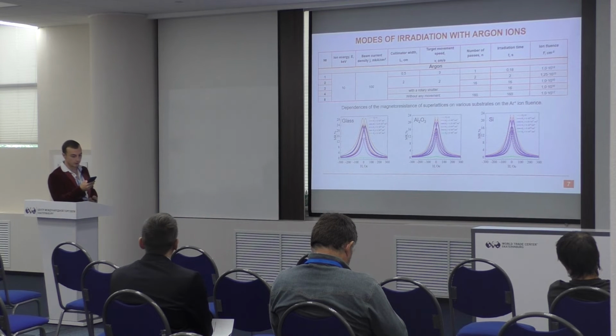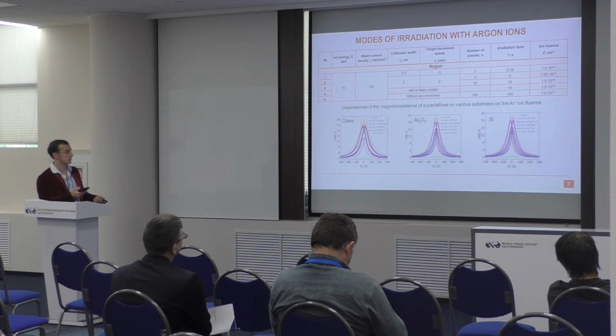The difference in values for a sample irradiated with and without heating on the sapphire silicon substrate is approximately 2%. The exception is the sample on the glass substrate. Without heating, the magnetoresistance value is almost 10% higher, comparable to a sample that was irradiated with the continuous ion beam.